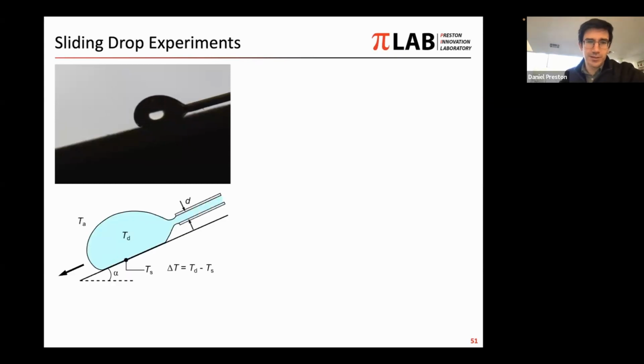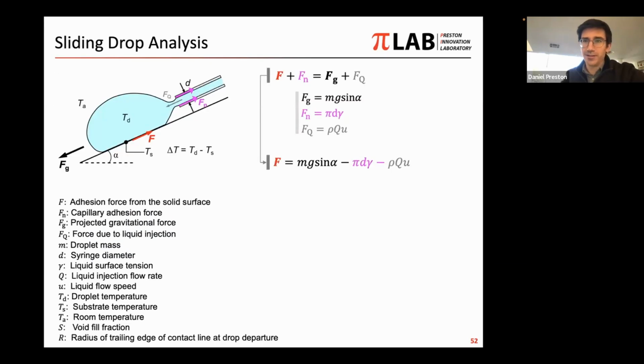We look at the cross-section schematically, and we can see a few different contributions to the force balance analysis. So we have some adhesion force, F in red here, and then we would also have some force that's due to maybe some surface tension effect at the needle. We have some gravitational force, the weight of the droplet, and we also have some force due to the flow coming in and stopping. A lot of these terms are constant.